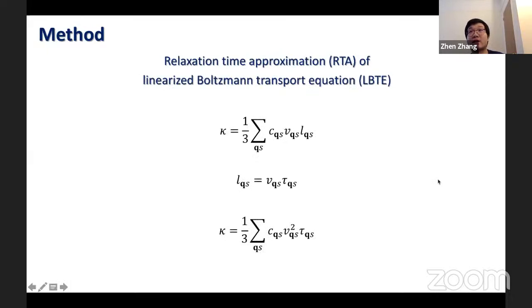From the relaxation time approximation of the linearized Boltzmann transport equation, we know that the lattice thermal conductivity equals the summation of a phonon's specific heat times velocity times mean free path for all phonon modes over the Brillouin zone. The phonon mean free path equals the velocity times the lifetime. And at high temperature, the heat capacity is approximately kB, the Boltzmann constant. Therefore, from the quasi-particles, we can obtain the phonon velocities and the phonon lifetimes. Then we can calculate the lattice thermal conductivity.